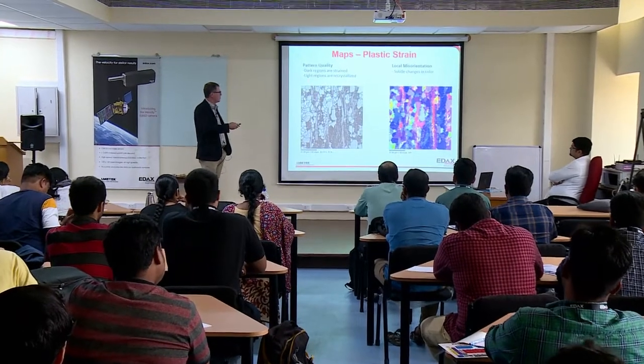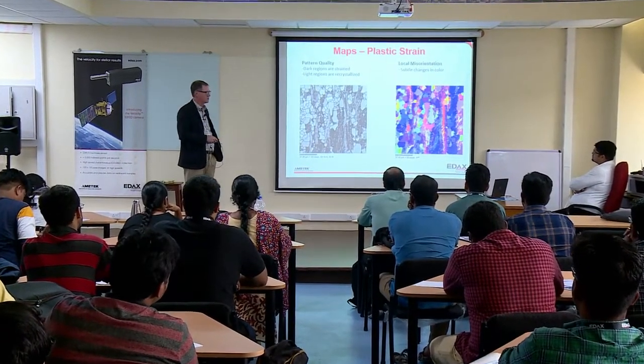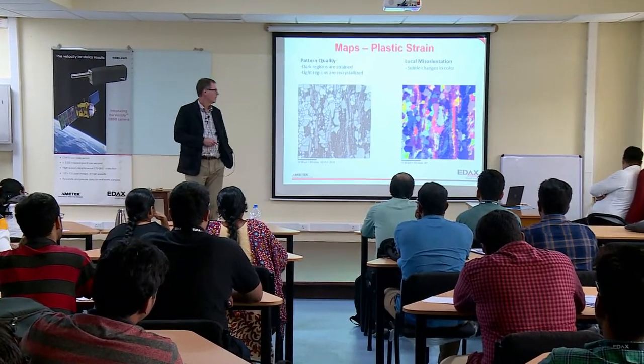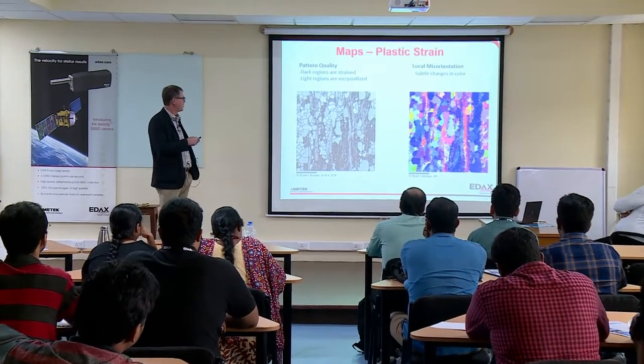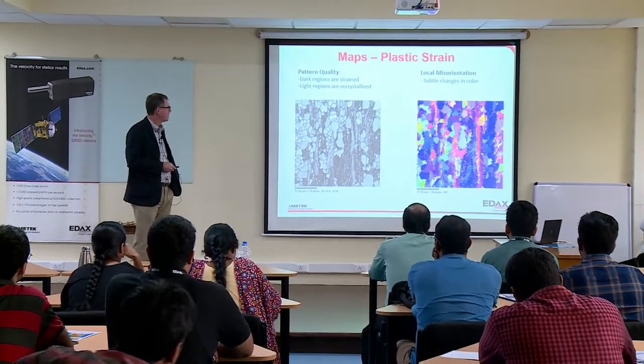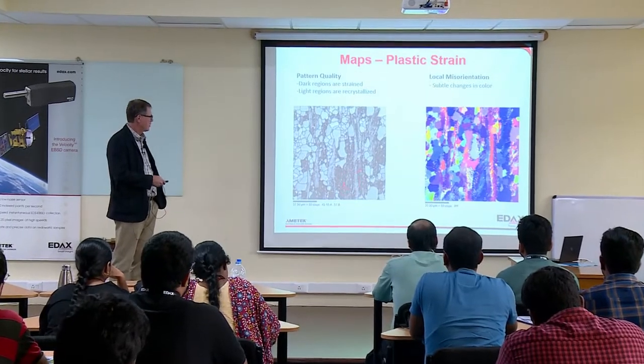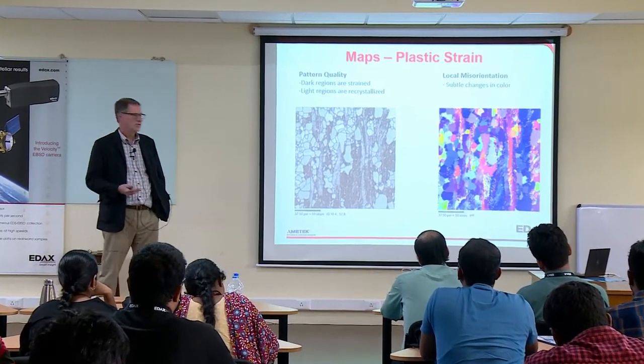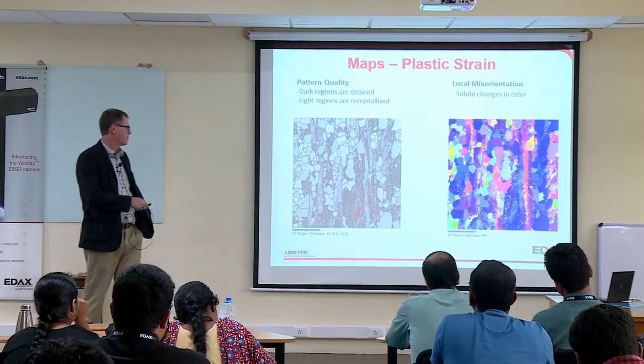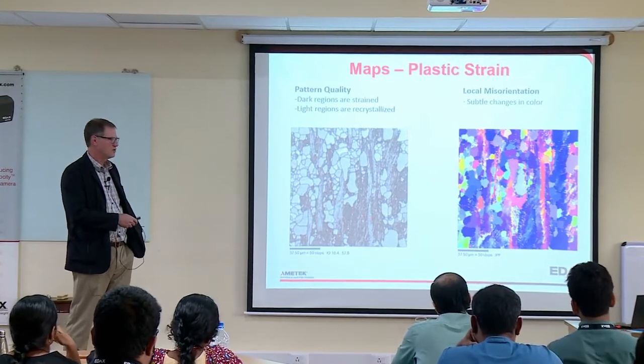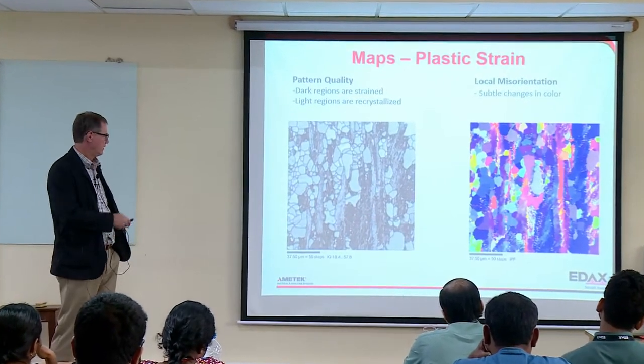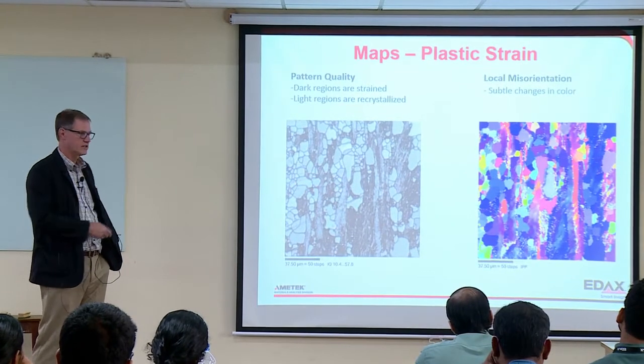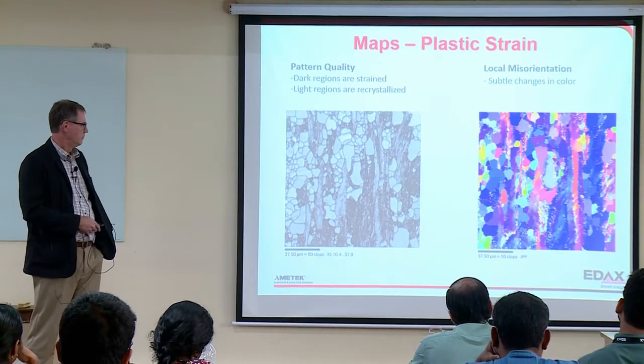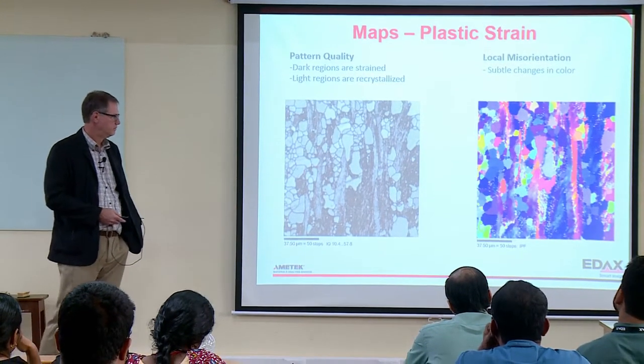So you can create maps based on these two ideas to see where the deformation is in your material. So this is what we call a pattern quality or image quality map. The dark regions here are because the patterns are poor. This shows the quality of the patterns. So the dark regions are poor patterns, which indicate strain. And the nice clear grains are recrystallized material, and they produce nice sharp patterns.